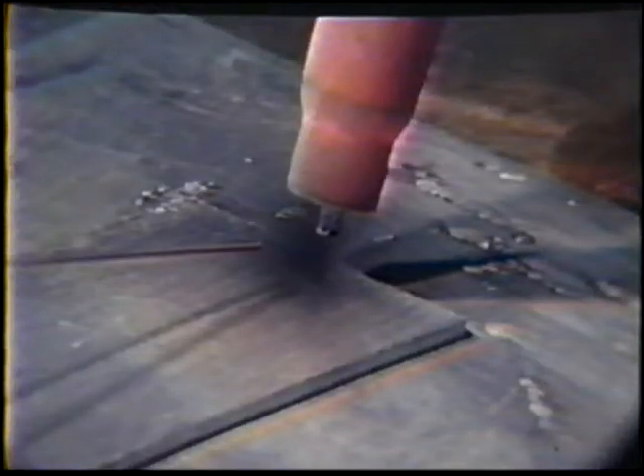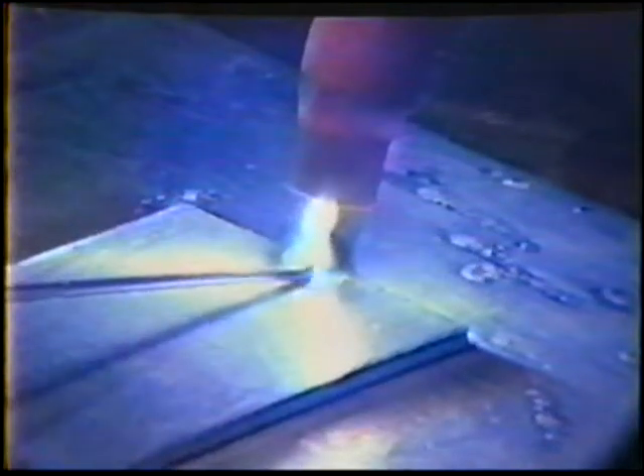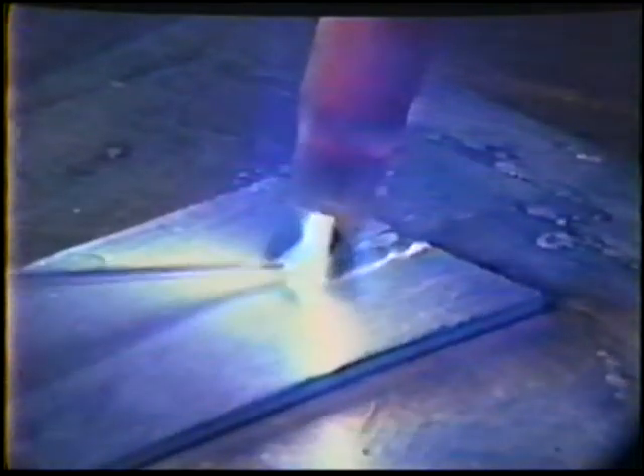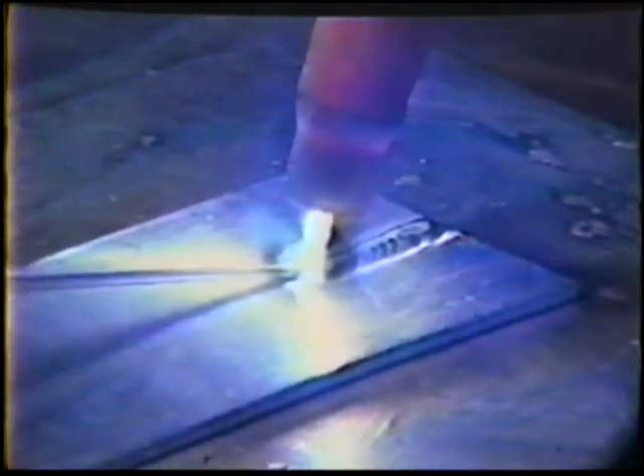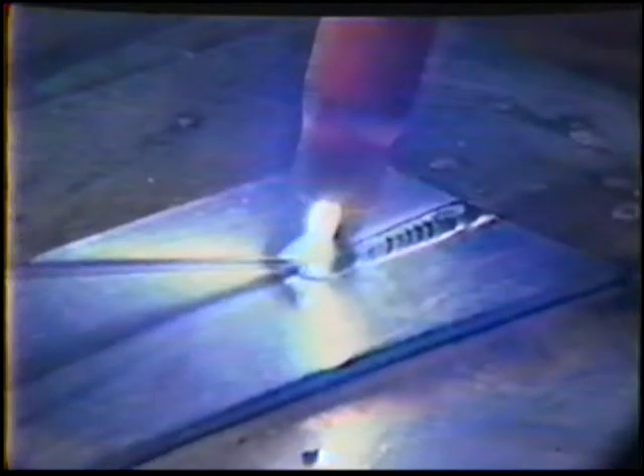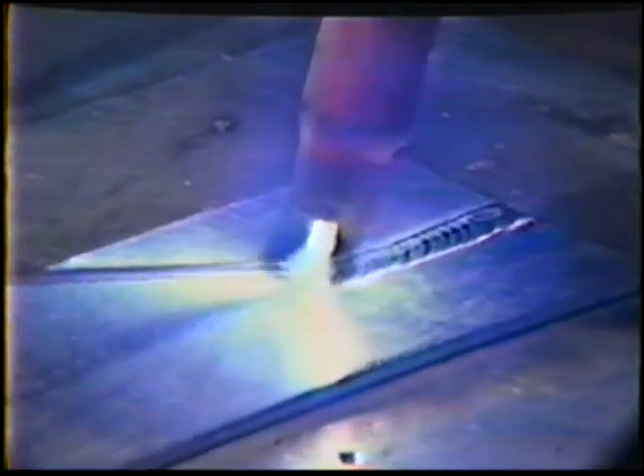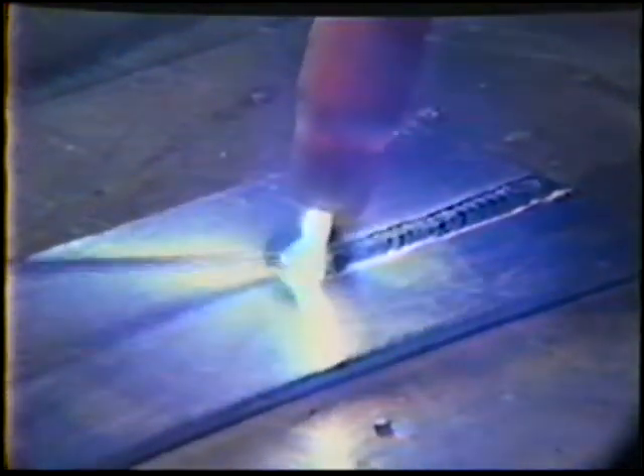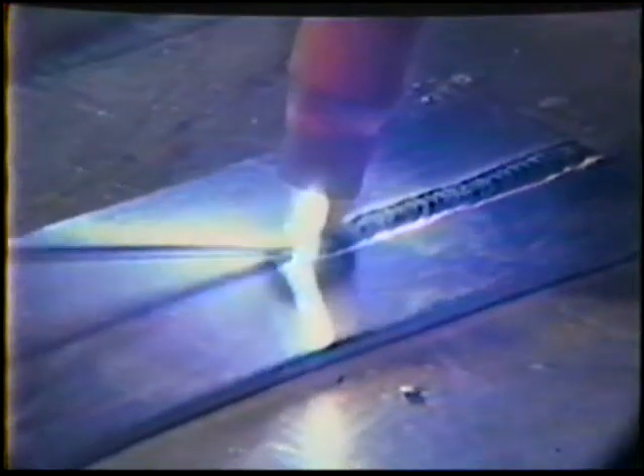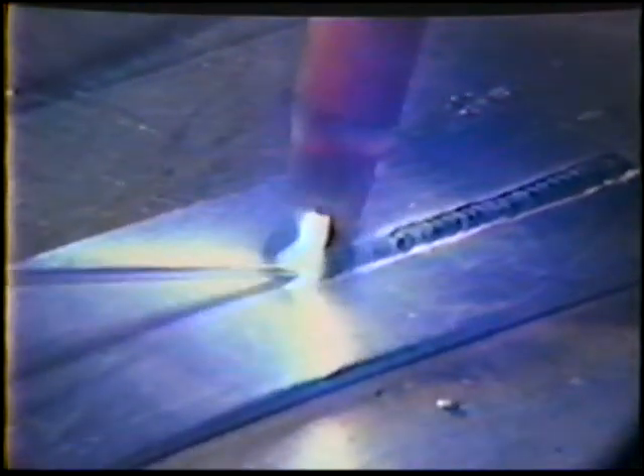Lower your helmet and start the arc by pressing the foot pedal and press until the proper heat is achieved to form a puddle 2 to 3 electrode diameters wide. Use the dip technique to add filler metal to the puddle. The rod is dipped in and out of the leading edge of the puddle as the torch moves evenly along. The filler should be added in even steps to maintain an even ripple. Keep a 1 electrode diameter arc length.